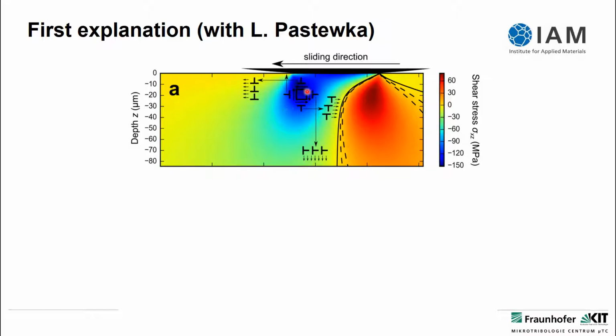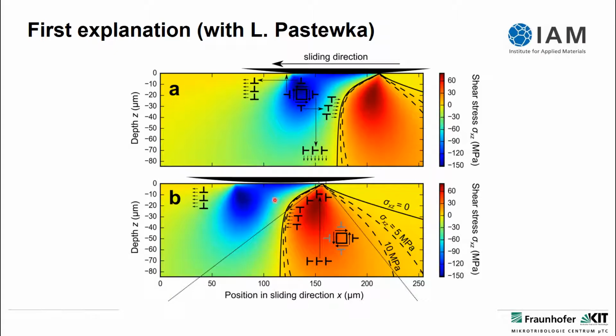And the most interesting ones are these edge dislocations oriented like this, because they will be pushed down further into the subsurface material, but as sliding progresses, these dislocations will cross over the zero shear stress line, this solid line here, to the positive shear stresses, and will be pulled up towards the surface again.